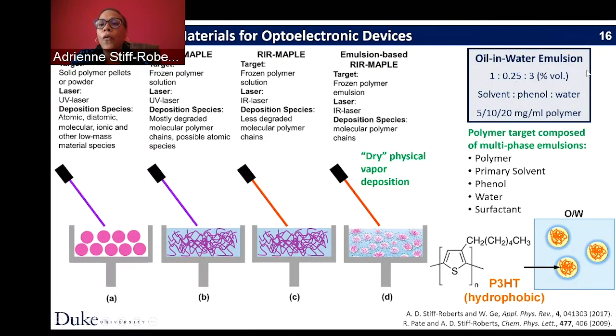So our targets are frozen oil and water emulsions. But these aren't simple, just oil and water emulsions. They have 5 different components. You have the polymer that you want to deposit. You have the primary solvent, that primary nonpolar solvent that it wants to dissolve in. And then a secondary solvent that also has OH bonds, but is low vapor pressure so that the target doesn't just sublimate in the vacuum of the chamber throughout the growth. We use a continuous phase of water, and this is the matrix. This is what is resonantly absorbing the laser energy. Then we have a very small amount of surfactant to keep this emulsion together just long enough for us to flash freeze this target solution in our growth chamber.